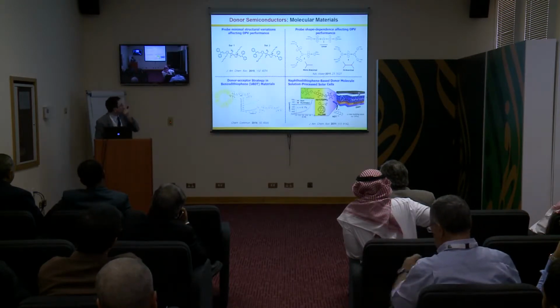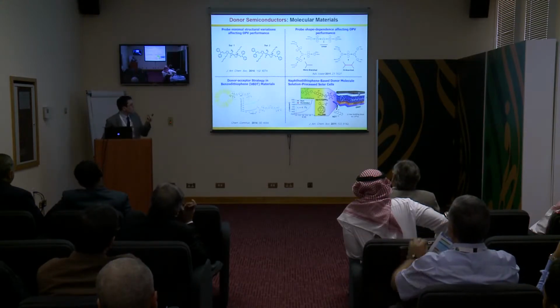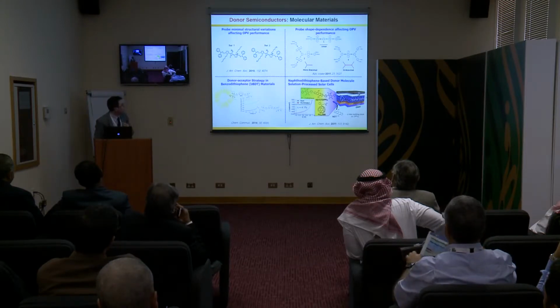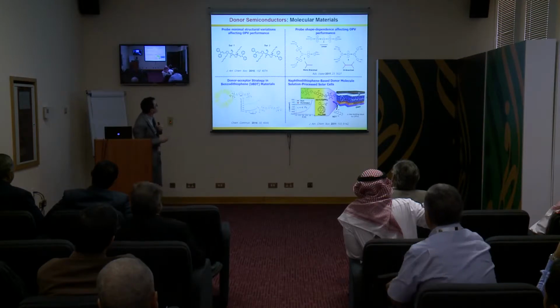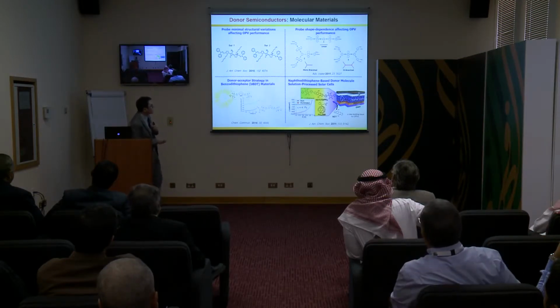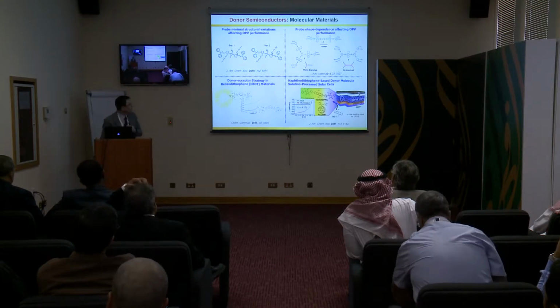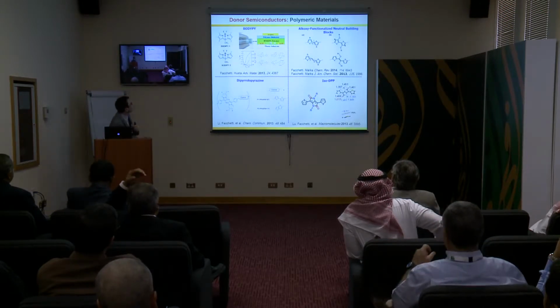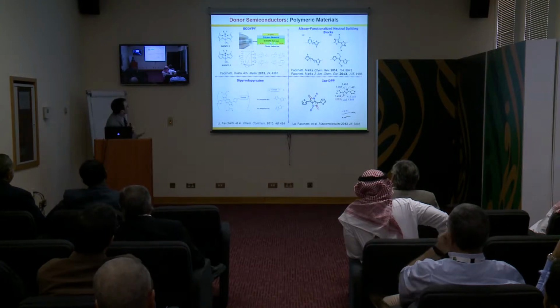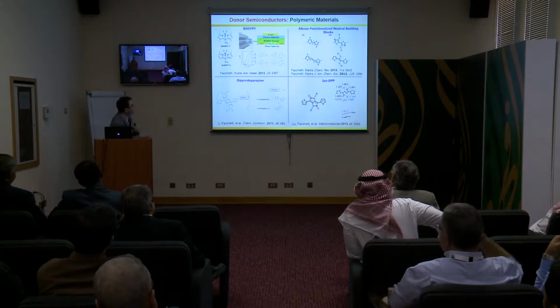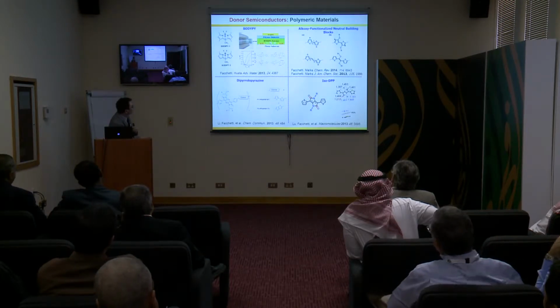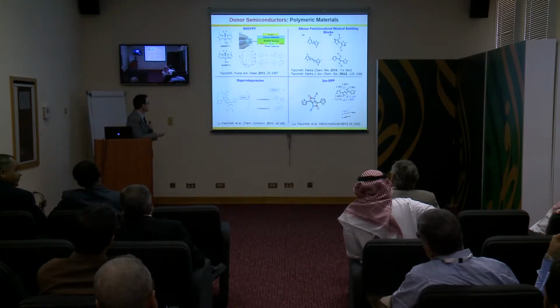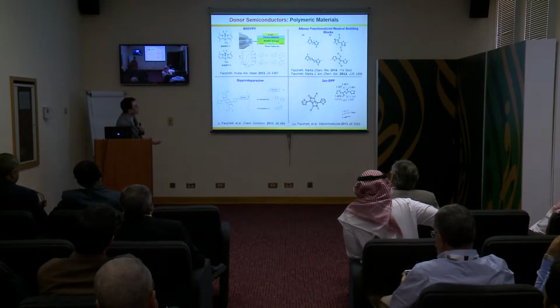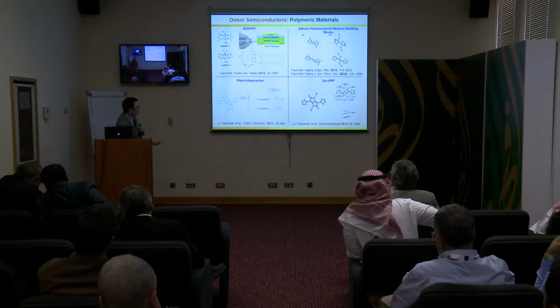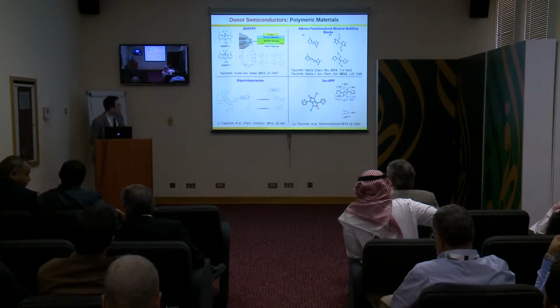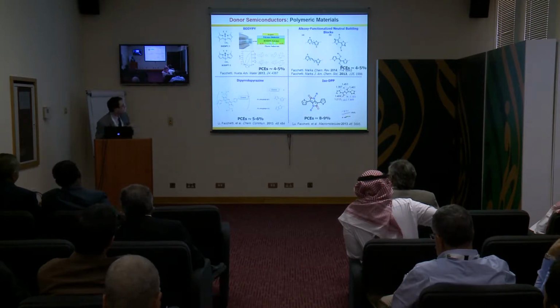We have also done quite some work on developing the photoactive layer molecules, looking at the donor semiconductor. These are some of the small molecules we developed a few years back, very, very simple systems. More recently we looked at more donor-acceptor systems as expected. They work better in terms of efficiency. And also looking at polymer donors. We look at, for example, this borazine type of structure, this thiazole, this more extended DPP type of structure based on a pyrazine heterocycle, and this which we call isomeric DPP, where we switch the nitrogen and the carbonyl to make a different heterocycle compared to the conventional DPP. And these are some of the efficiencies we have reported.